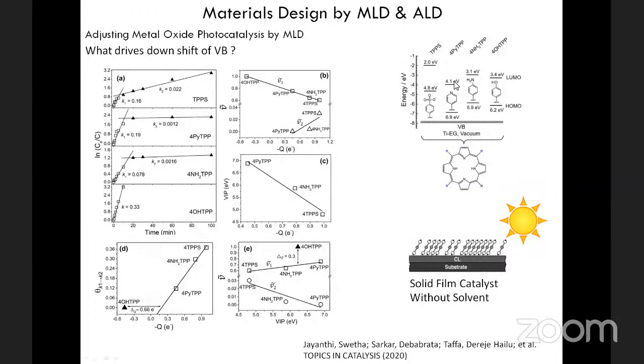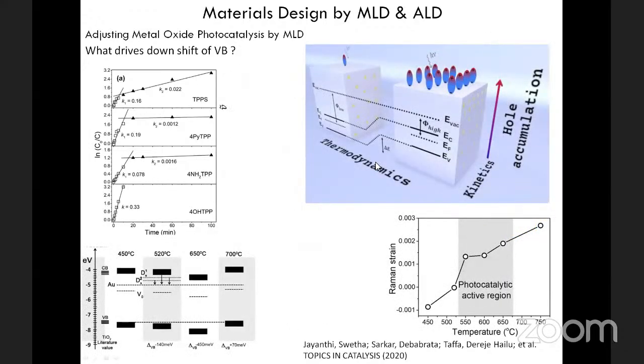And then what we saw is very interesting, that unlike the single exponential kinetics, first order kinetics of benzoic acids, for porphyrins, we obtained two regimes, fast and slow regime. And you can see here that you have 2 regimes, and this is for each of the porphyrins. And here again, we looked into the electronic details of these molecules and how they correspond to their activities. Because of time, I will skip on and just summarize what we found. So we found the following.